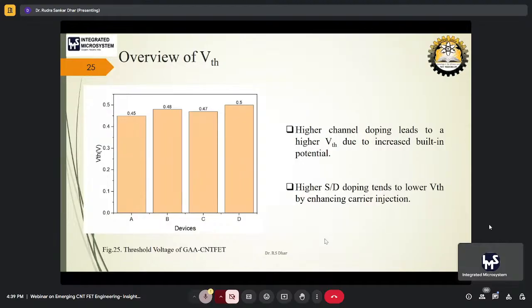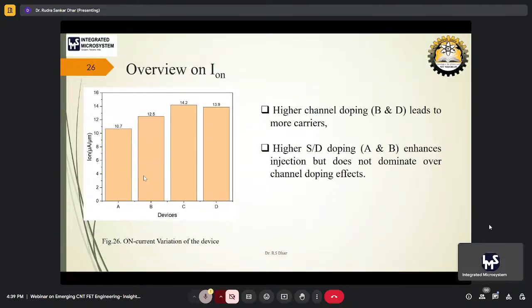So this is the threshold voltage variation based on the 4 devices. What we can see is that 0.45 is the lowest threshold voltage that we are getting, for our device A. Higher channel doping leads to a higher threshold voltage due to increased built-in potential. Higher source drain doping tends to lower the threshold voltage by enhancing carrier injection.